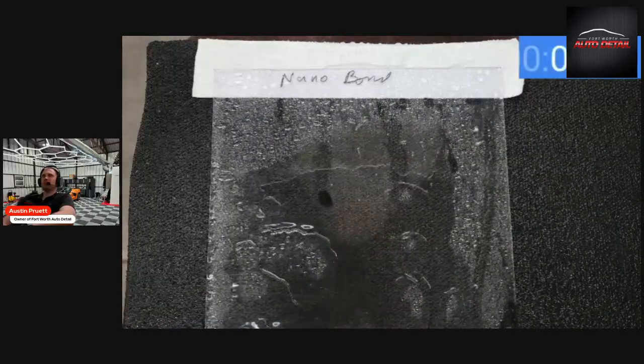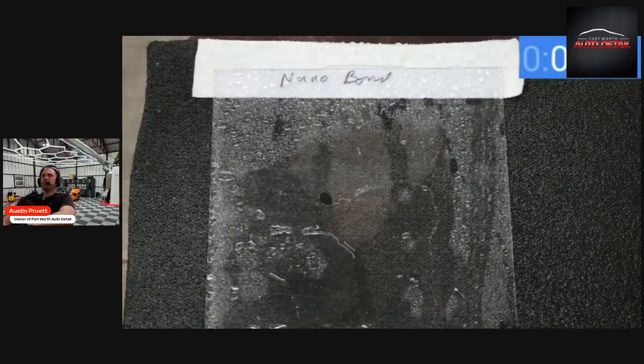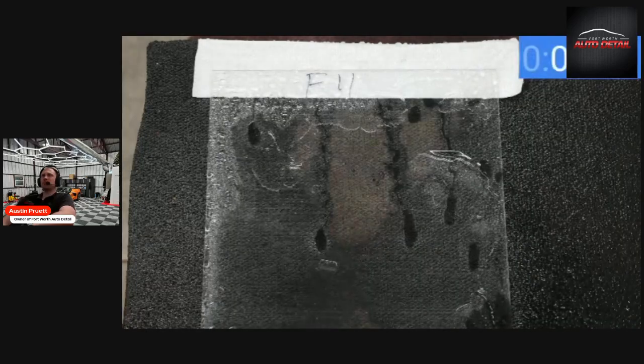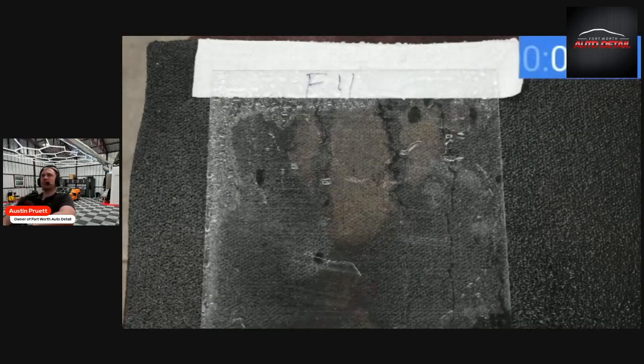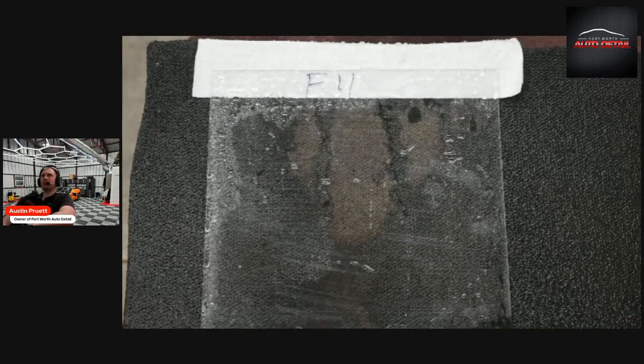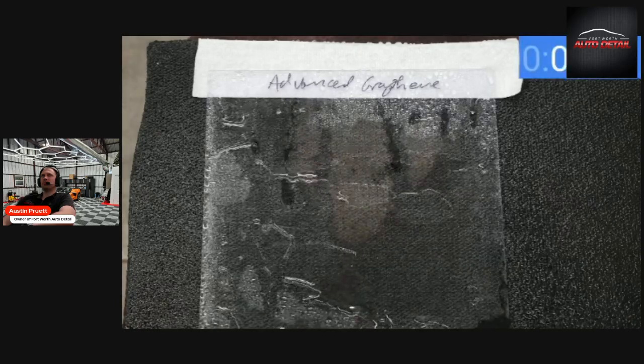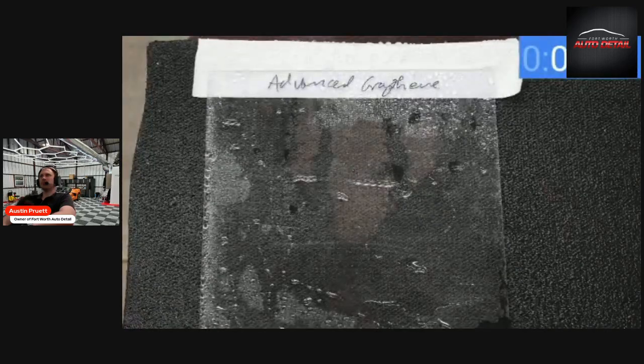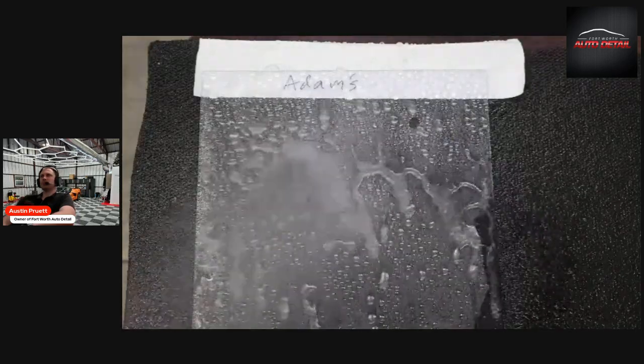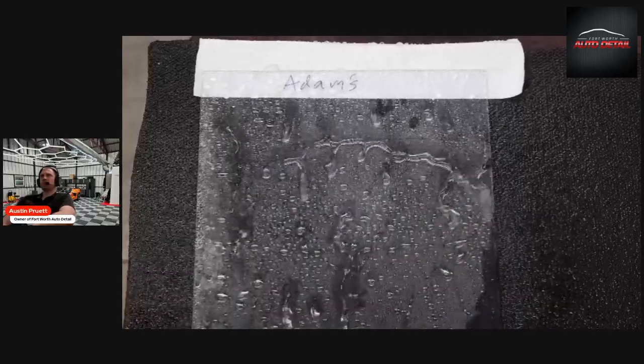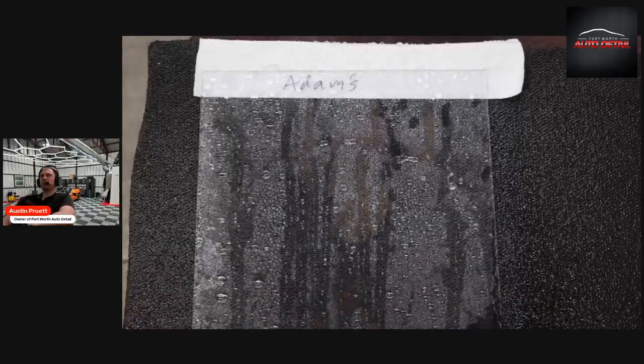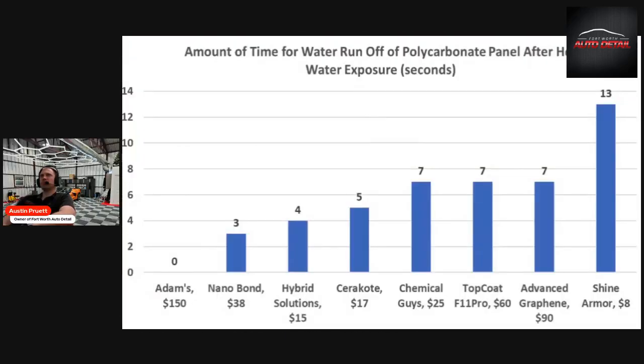And a small sheet of water formed on the Nanobond and cleared in 3 seconds, the fastest time yet. A larger sheet of water formed on the F11, and it took 7 seconds for the water to clear the test piece. And the Advanced Graphene performed about the same as the F11, at around 7 seconds. After 4.5 hours of warm and hot water spray, the water is not able to form a sheet on the Adam's. Very impressive! So the Adam's came out on top for warm and hot water exposure. Nanobond finished in second at 3 seconds, and Hybrid Solutions 4 seconds.